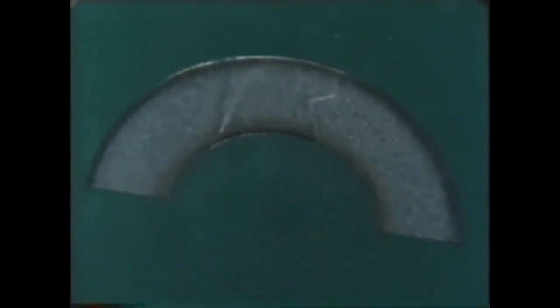But because of prolonged heating at a high temperature, grain growth occurs. The high carbon case will have a coarse, crystalline structure, and it has a tendency to crack under stress. This coarse grain has to be refined, and the case hardened. And this is the next stage in the process.